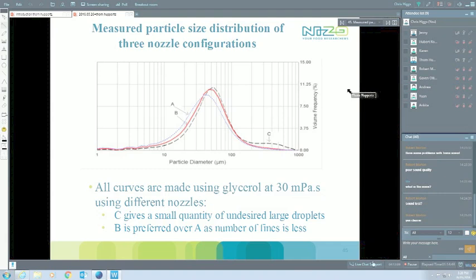combination. And of course, what we like to see out of that is our different particle size distributions, and really start looking at what is the most optimal one here. Okay. Just 3 different conditions compared there, A, B, and C. What we basically see is that C gives us a lot of large particles, so we don't want to use that. That's going to give us issues. A and B don't give that. They nicely narrow down the way we would like to see it. A is a lot smaller from this perspective, still quite a bit more small particles, and so, using a system like this, B seems to be the preferred combination.